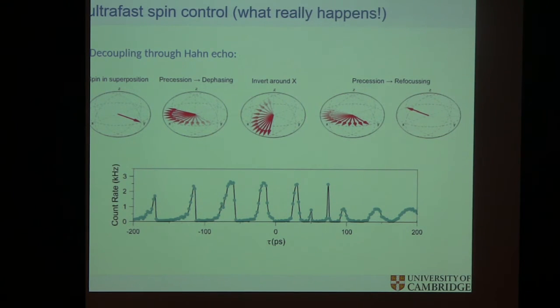So the reason you see this is because it's a massive feedback system of nuclear spins being polarized, meaning shifting the Zeeman splitting of the electron spin, and therefore your optical transitions shift. So the phase you acquire is different. So the whole thing tumbles as you try to optically act. So you have to sort all of that out to be able to get a clean profile.